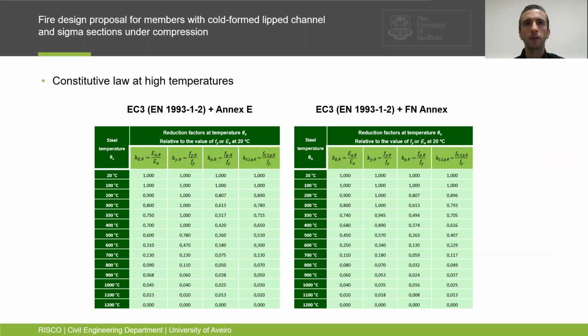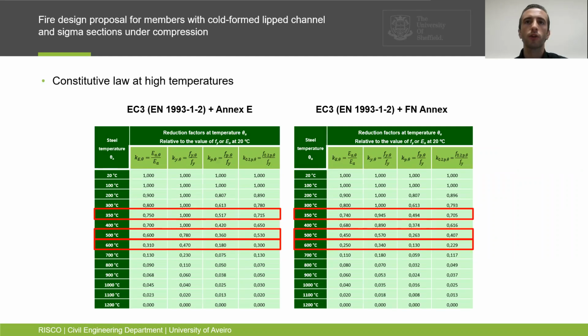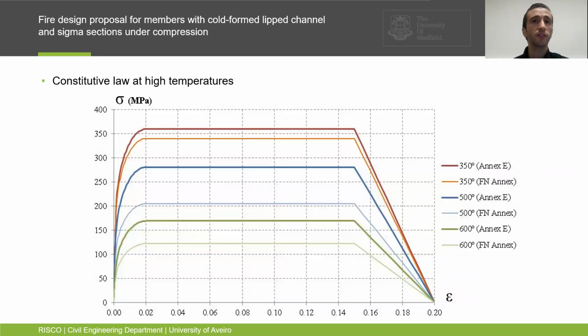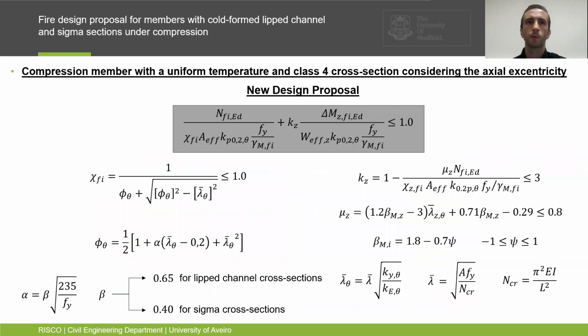Here I presented the different steel constitutive laws according to the respective annex, where the French National Annex presents reduction factors with lower values. As you can see here, in this case for 350, 500, and 600 degrees.